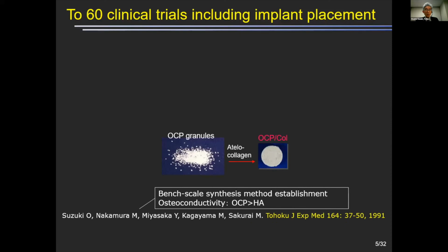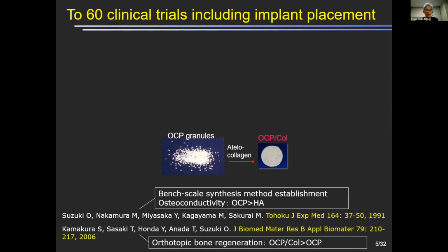and the osteoconductive property was found by establishing a bench scale synthesis method. And we found OCP had a higher osteoconductivity than hydroxyapatite. And then we developed OCP collagen, which has a superior osteoconductive property than OCP alone, through collaboration with Nippon Ham Meat Company. And then the